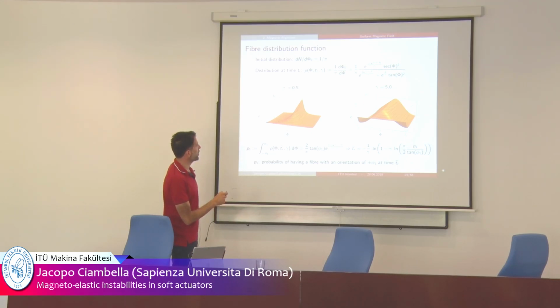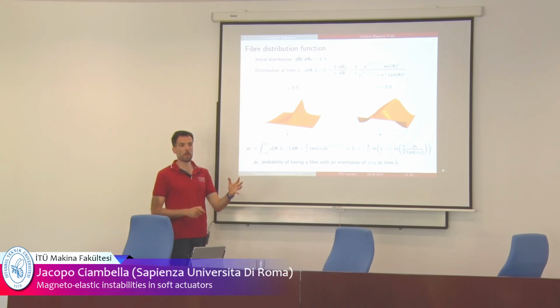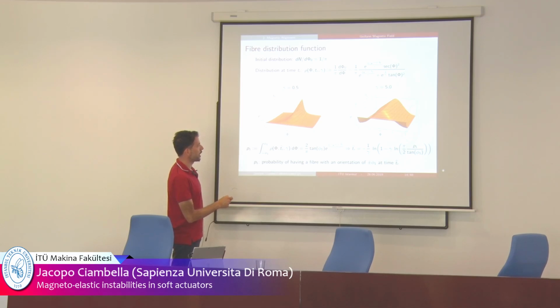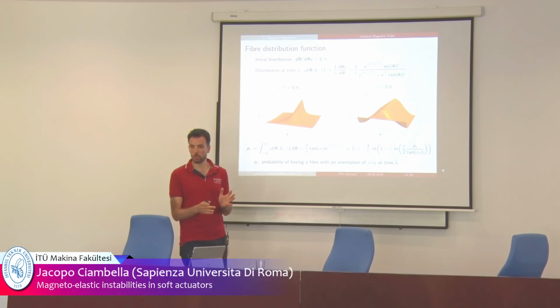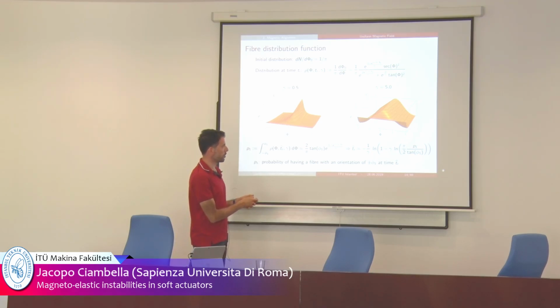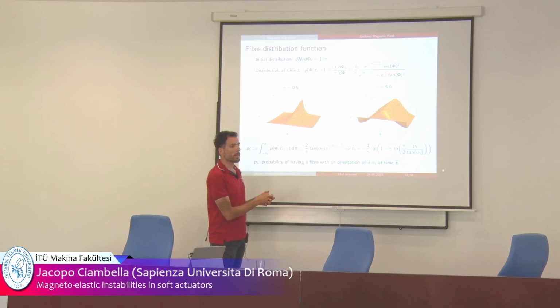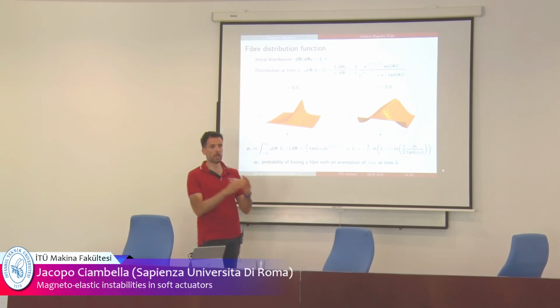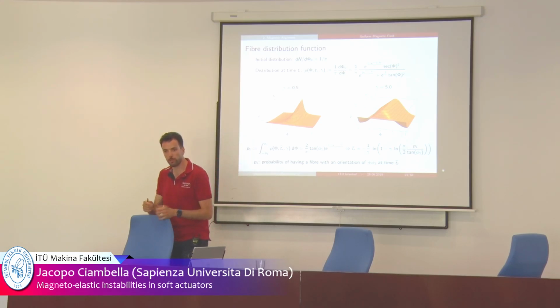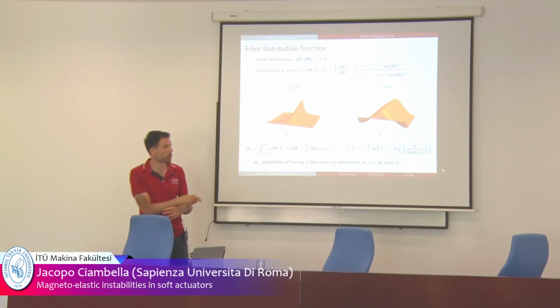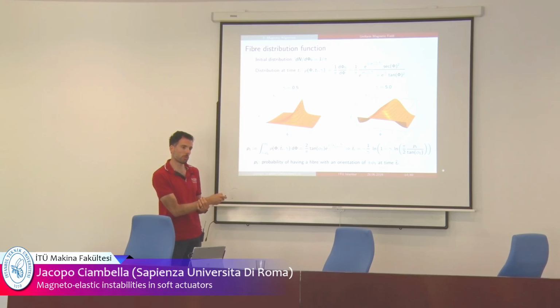And then what is happening with gamma equal 0.5, so a relatively low gamma, the particles will orient around 0, and you end up with most particles oriented around 0. If gamma is larger, meaning that the curing time is much shorter, you start with a uniform distribution, but you end up with a much wider distribution of the particles, meaning that not all the particles have time to orient themselves. Okay, so the scattering angle is much larger.